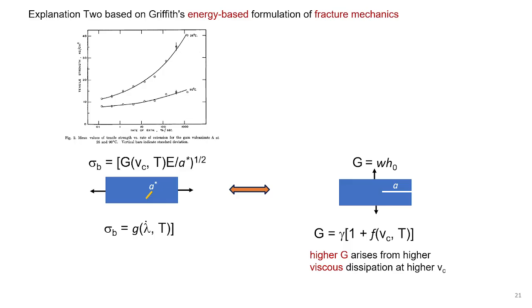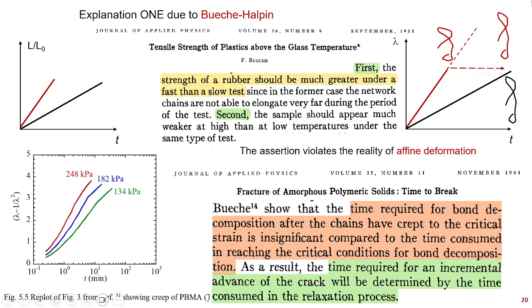And that claim, of course, completely violates the reality of affine deformation, which is why I reviewed for you what affine deformation is. Your experiment was not a creep experiment. You do a displacement experiment. Once you reach that stretch, you have that molecular strand already.